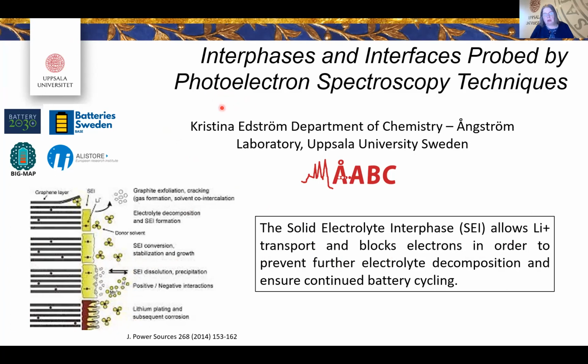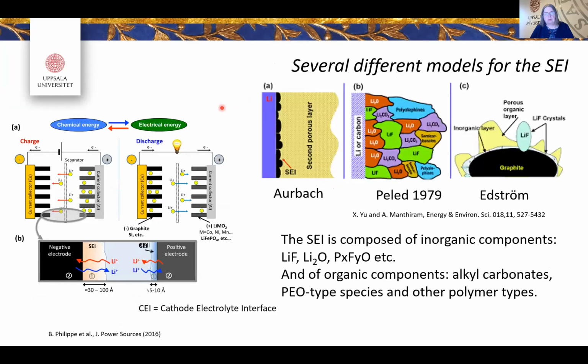I will show a lot of results using photoelectron spectroscopy, and a lot of the knowledge we have today is actually based on this technique, because if you look at the thicknesses of these SEI layers, they are in the range of 30 to 100 angstroms. There are very few other techniques where you have this surface sensitivity to really depth profile and say something about the composition of the SEI.